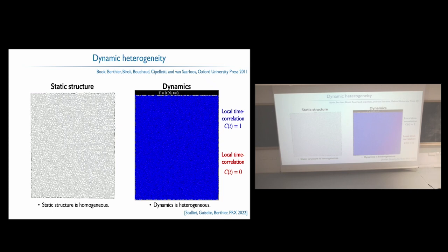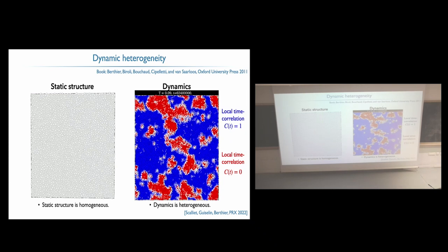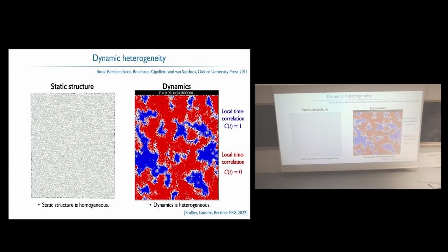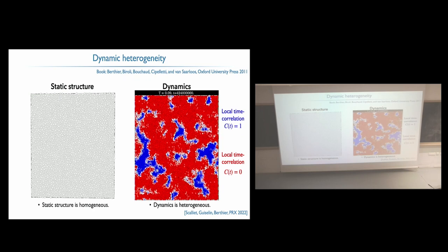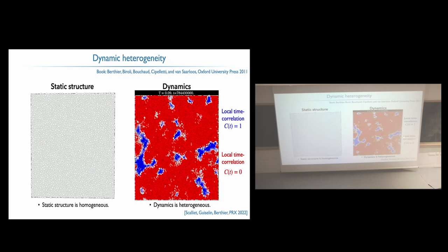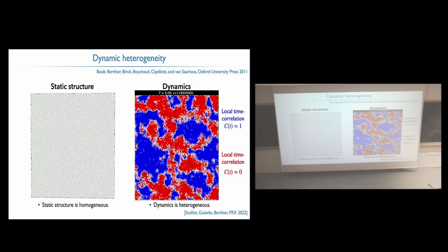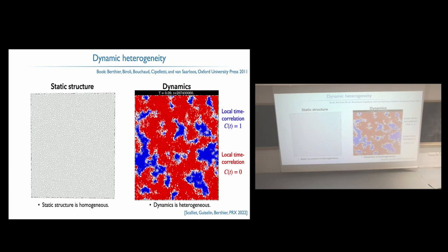But now, if you look at the dynamics, I'm going to show it in a specific way. I'm basically going to show whether locally the atoms have rearranged, so whether they flow or not. If they don't flow, they're blue, comparing time 0 with time 0, so nothing has moved. And if they're red, it means that they have undergone some flow. This is the movie that you obtain. These red regions are the regions where it flows, and these blue regions are basically solid. I think you would all agree that compared to the statics, where you don't see anything particular, in the dynamics you really have something extremely heterogeneous, with some regions that move very fast, and some others like this one, which move very slowly. This is the concept of dynamical heterogeneity.